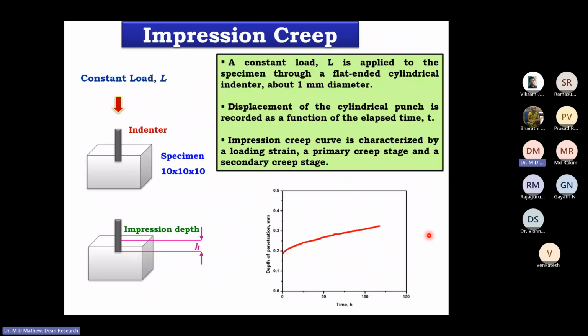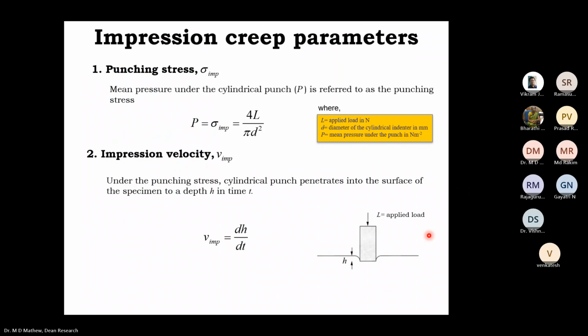So how do you analyze this creep curve and generate the important information that we would have got otherwise from a standard creep test? In this case, we have the load L. First, you calculate the mean pressure under the punch. You have a cylindrical punch of diameter small d, and you are applying a load, capital L. Under the action of the load, you can calculate the mean pressure under the cylindrical punch: sigma m is equal to 4L divided by pi d squared, where L is the applied load, small d is the diameter of the cylindrical indenter, and sigma m is the mean pressure.